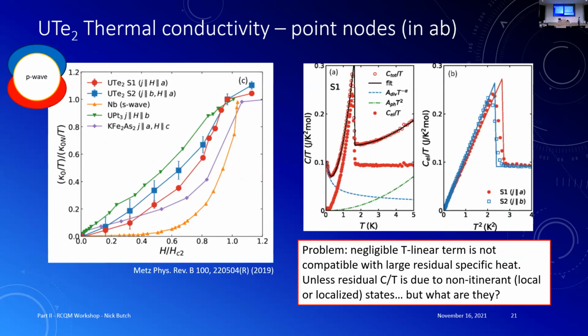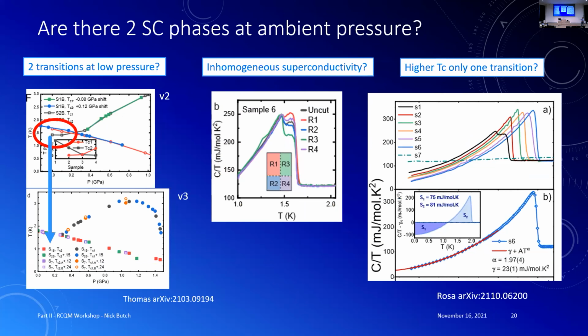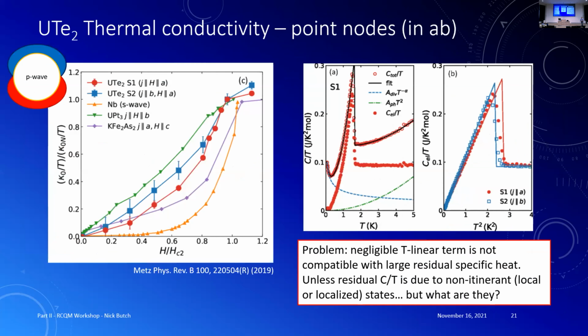Okay, second thing is, and they don't show that here. And again, I'm not saying anything, but every sample that we know of shows an upturn, including from other groups. And so the origin of this has been attributed to nuclear Schottky effect, for example, but it's inconsistent with thermal conductivity measurements, which suggests that there are no itinerant carriers, okay? Nothing that can transport entropy. So our supposition right now, and it's yet to be demonstrated, is that these are some localized, maybe magnetic fluctuation, something like this, but we don't really know.